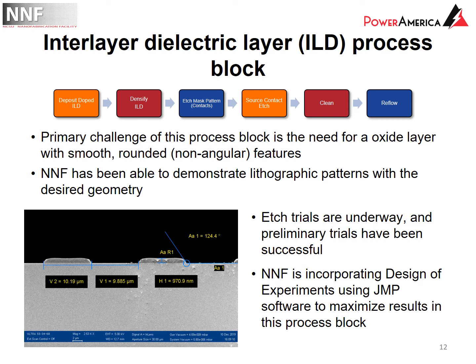The next process block we took a look at was the interlayer dielectric, or ILD, process block. What the ILD is, is the silicon dioxide layer which insulates the top metal contacts from the underlying gate structure of your device. And the primary challenge of this block is the need for an oxide layer with smooth, rounded features, as opposed to the sharp, angular features you typically get from etch and lithography. So we had to develop a whole new lithography technique in order to get the rounded features like you see here in the SEM image.